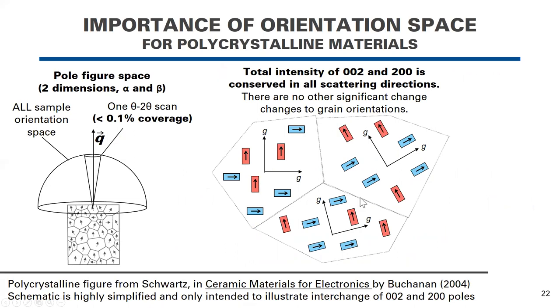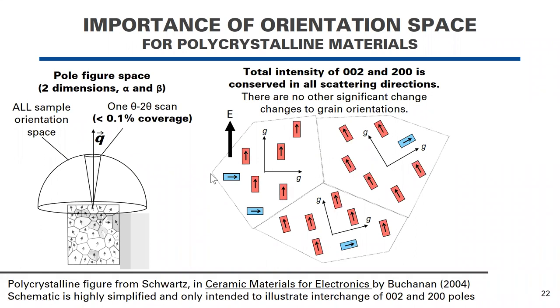Now, I tried to illustrate this in a schematic that I threw together this morning, so I hope it comes across well. You could imagine, and again, this is a highly simplified schematic, so I've got the disclaimer down here at the bottom. You could imagine that with applied electric field, you could reorient some of these domains into a more favorable direction. But if you're looking at either a G vector here, or here, or here, you can see that domain reorientation is conserved if you consider the total intensity of both.